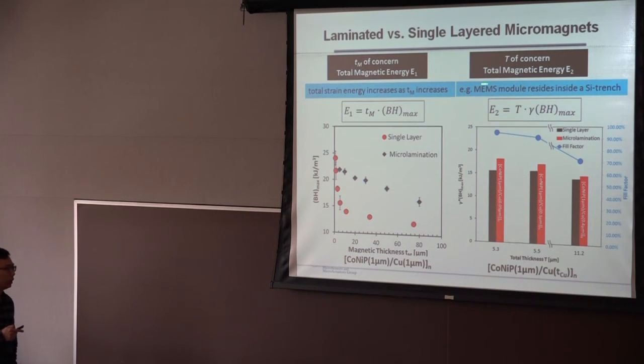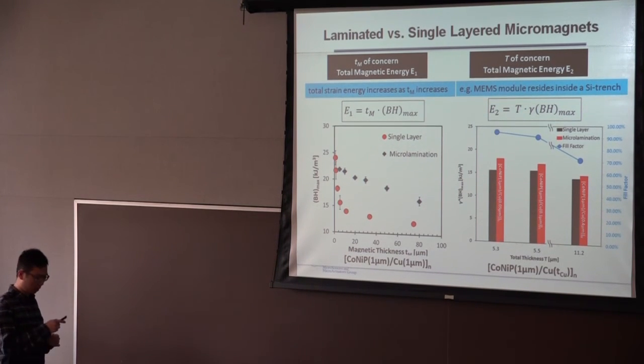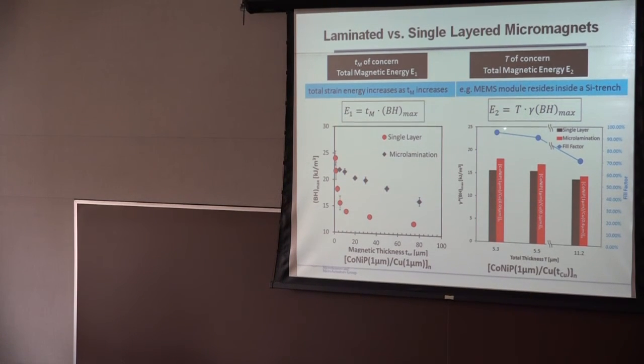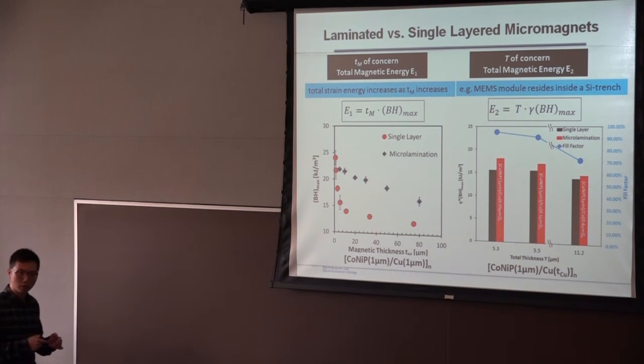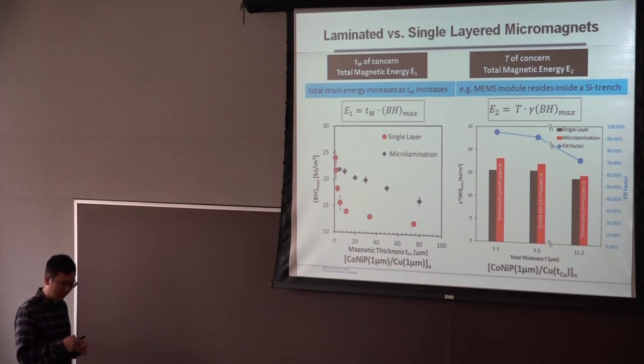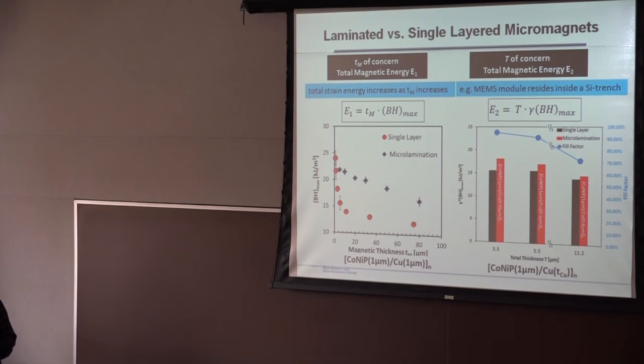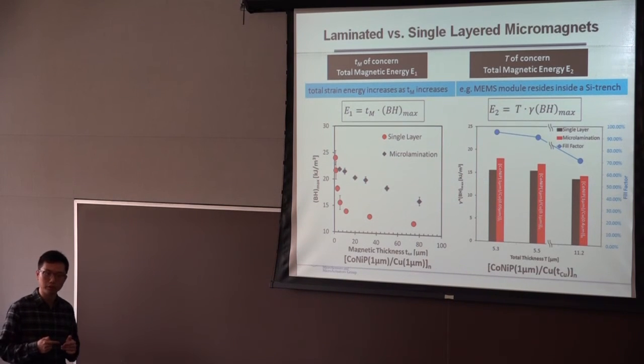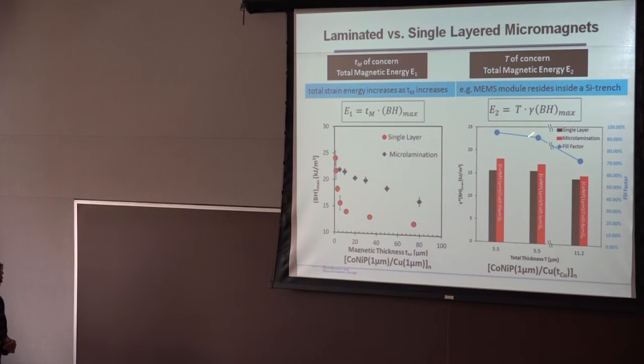Another case is when the total thickness is of concern. For example, say the MEMS module resides in a prefabricated silicon trench, so the total thickness is constrained. Then we have to think about the strategy here. Even if you decrease the copper interlayer thickness, so that you preserve your magnetic properties less, this will be compensated by the fact that you now have a larger magnetic thickness, because the overall thickness is constrained. So in this case, it's the total thickness that matters.